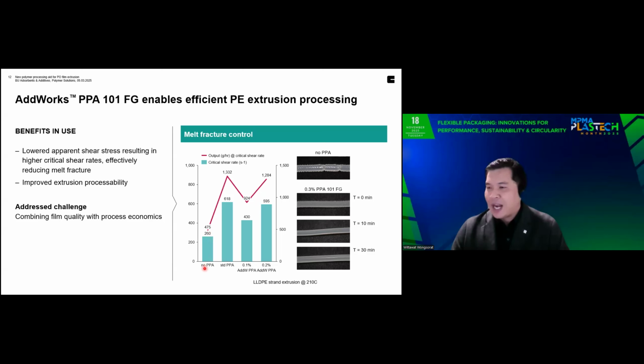From the bar graph, when we did not add any polymer processing aid, the critical shear rate is about 260. When we introduce a conventional PFAS product in the market, using 500 ppm of PFAS, the critical shear rate goes up to 618. We can achieve a similar level of critical shear rate when adding 2,000 ppm of our product.